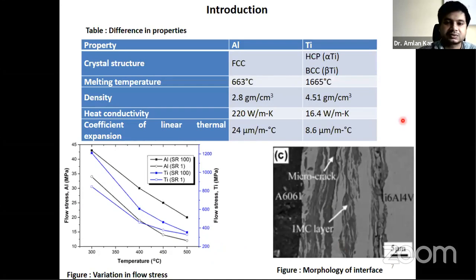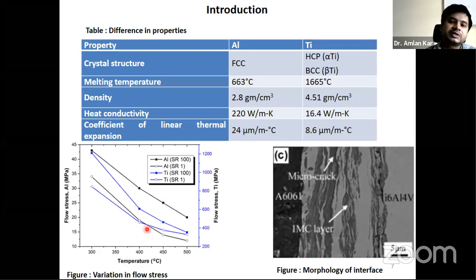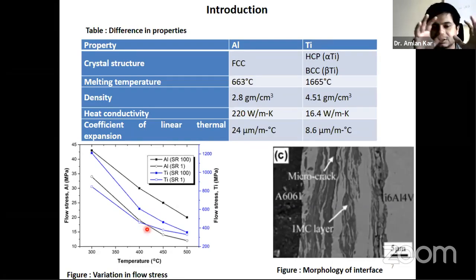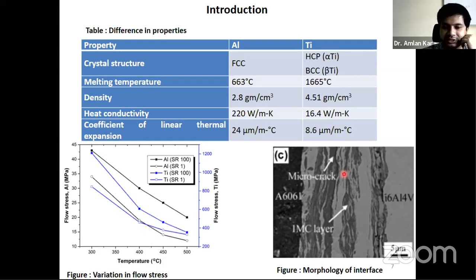And I was telling you, you can see here, there is a crystal structure difference, a difference in physical property and heat conductivity, and therefore there is a lot of inhomogeneity across the interface. And from this diagram, you can see there is a difference in the flow stress of aluminum and titanium. So you can assume that aluminum is not there, but the deformation is actually taking place on the titanium. If you nullify the aluminum deformation, and concentrate on the deformation of the titanium, you can see there is fragmentation, and on this fragment, aluminum is diffused, and therefore there is a reaction.